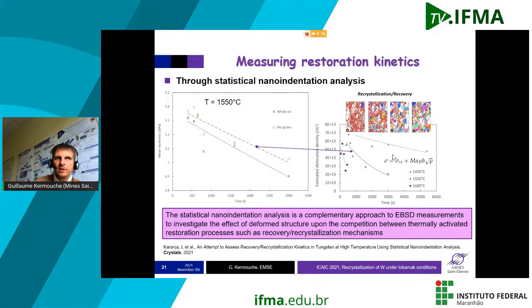Recovery, what does it mean? It means this is the decrease of dislocation density in the material. And from hardness, we can relate hardness to the stress, and we can relate the stress to the dislocation density. So we are able, with this kind of measurement, to estimate the dislocation density and to analyze the decrease of the dislocation density with time. Okay, and from that, we are able to measure the parameters that are related to recovery for the different temperatures that we tested. So we use this kind of data to evidence recovery.